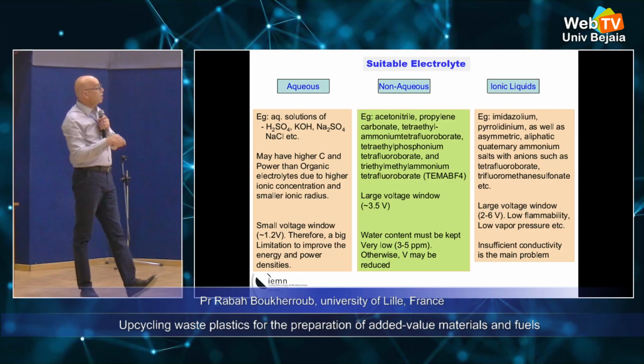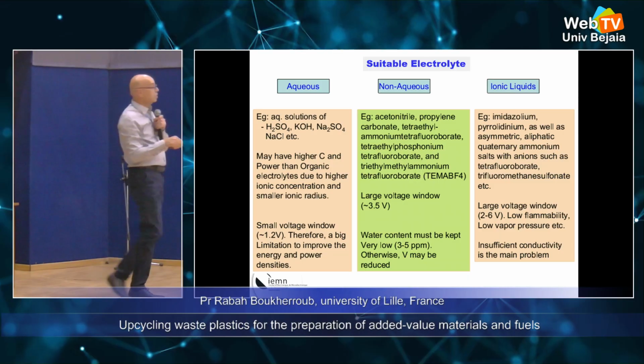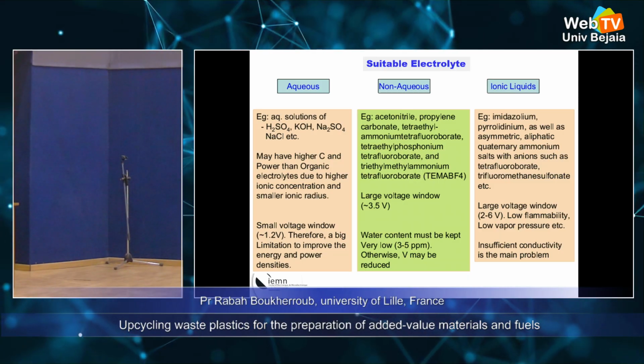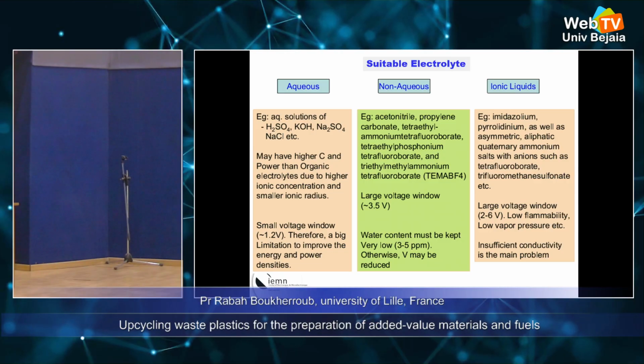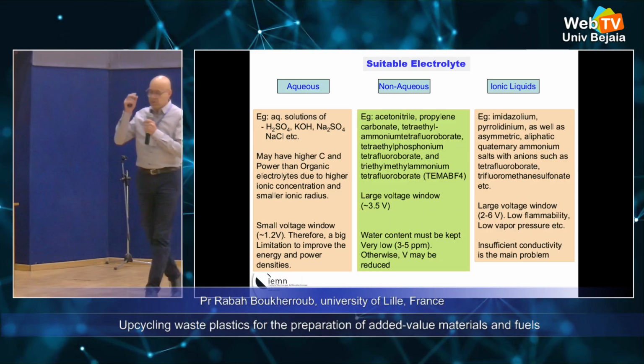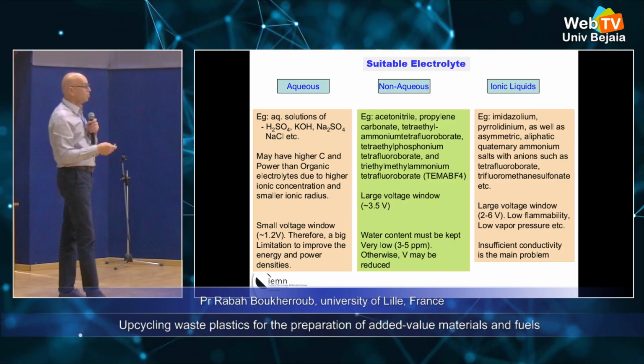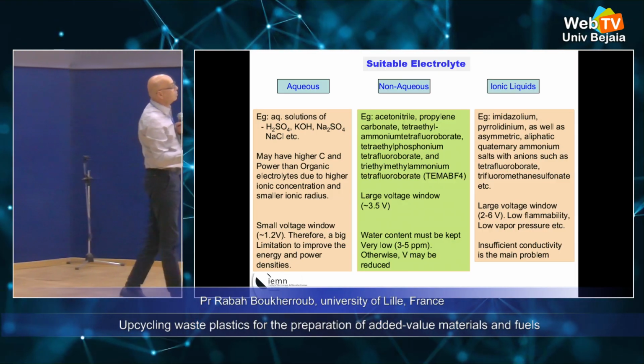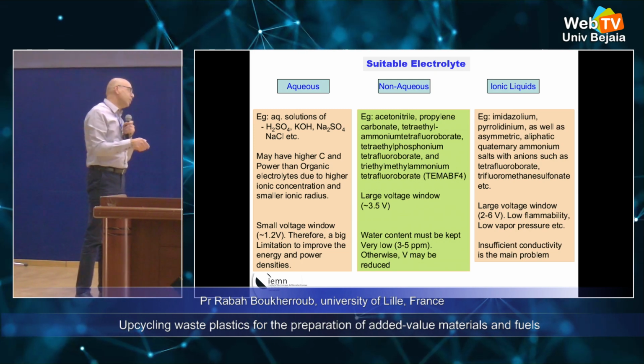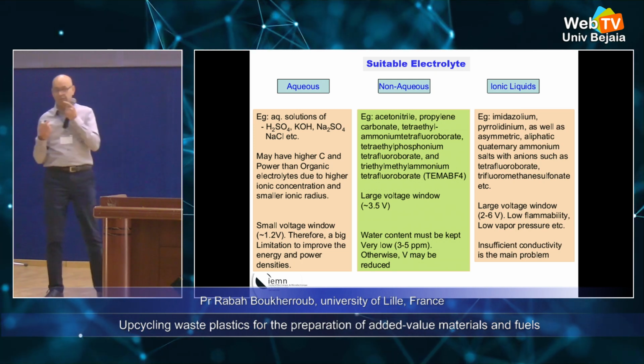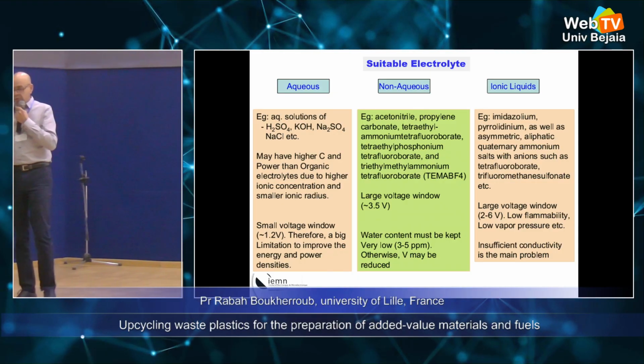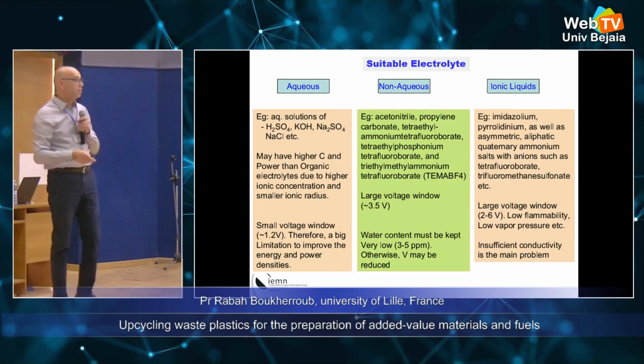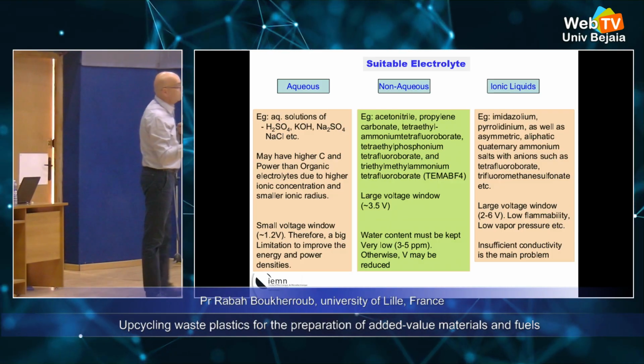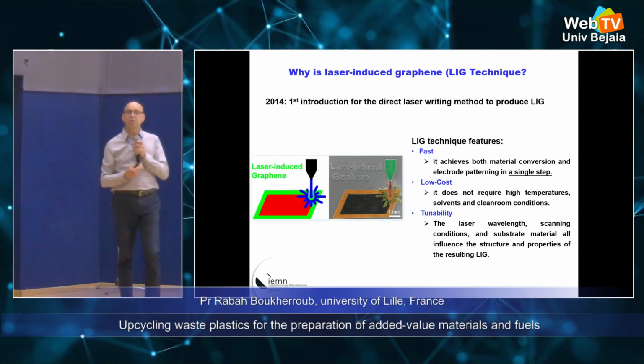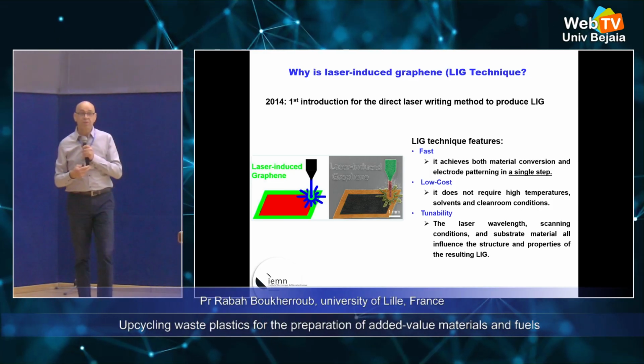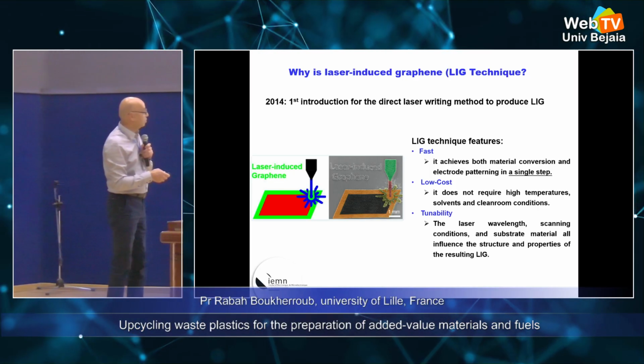You can use non-aqueous, organic electrolytes, and you can reach up to 3.5 volts, but you have to keep the water content really very low, which is not easy, especially for some polar solvents, so you can always capture some water. So the ideal here is the ionic liquids, but again, they also have their own problems because they are very viscous as well. So the motion or the diffusion of ions is quite limited. But the ideal is to make what you call an all-solid supercapacitor. It means you have polymer gel instead of having these organic or water-based electrolytes.